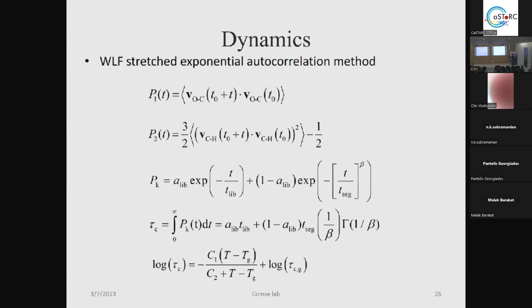You can see here in the first and second Legendre polynomials that we take into account the vectors, and from these we take this parameter in order to parameterize this equation to have parameters like a-lib, which is the parameter for libration of atoms around their skeletal bond, and the characteristic times of this libration, which is the T-seg and beta. And from these parameters we calculate the relaxation time, and from the relaxation time we calculate the Tg.